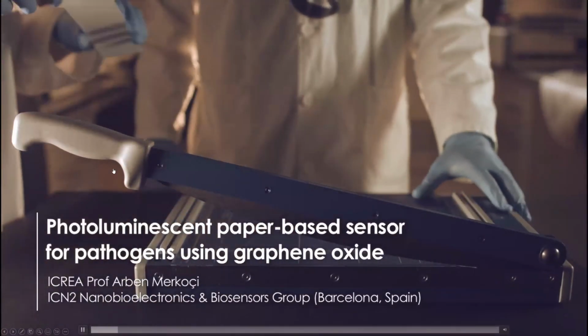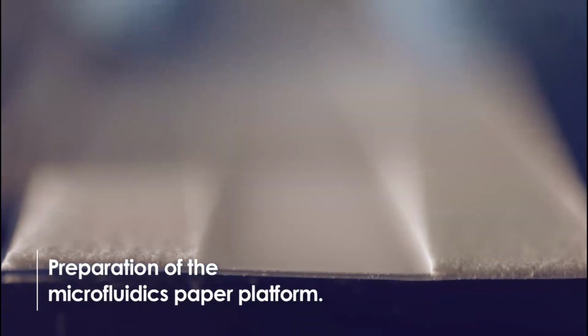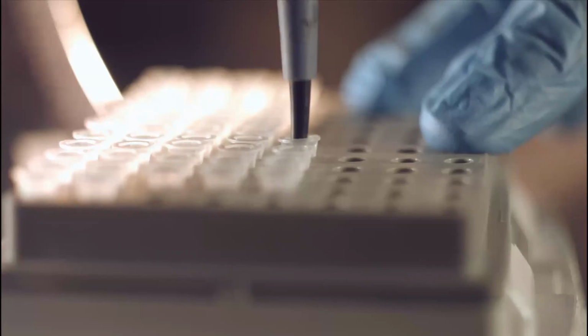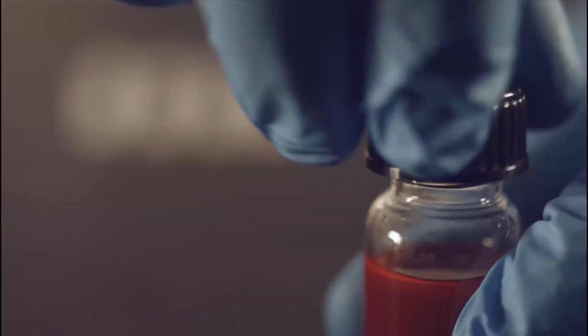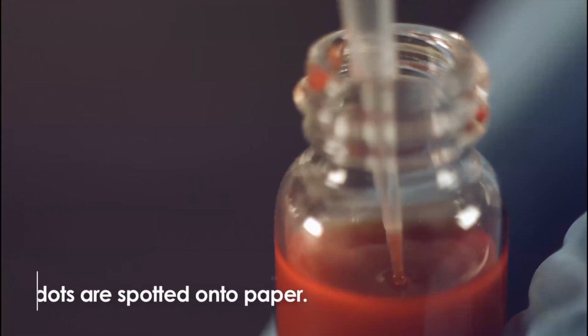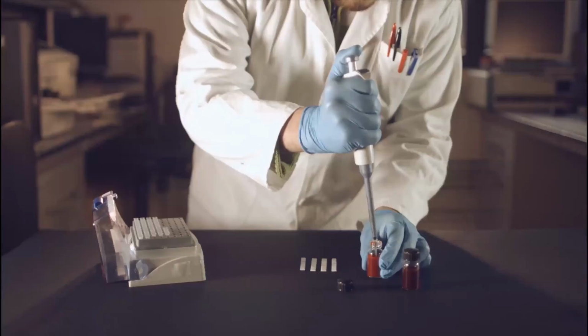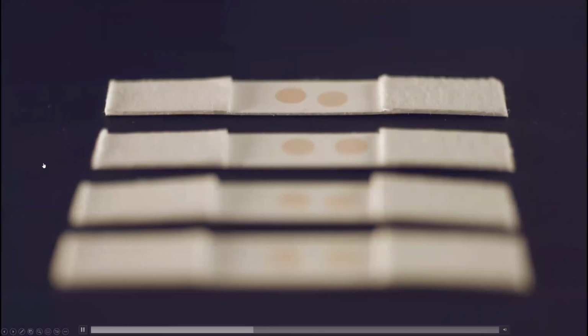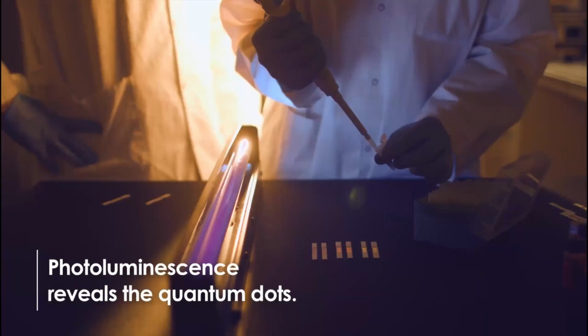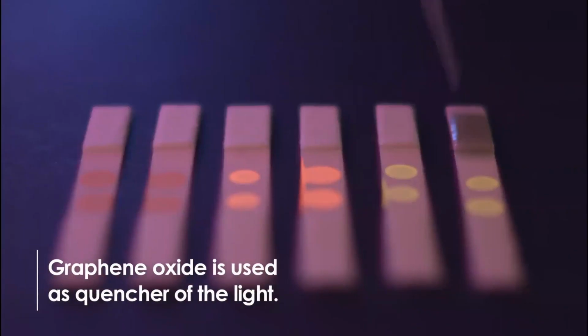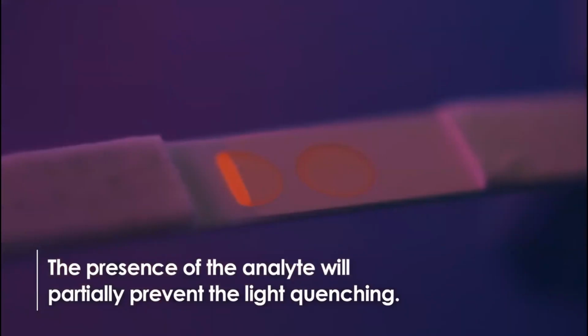So this video is showing how we prepare these devices and how we prepare for the measurements. First of all, you select the paper, you introduce quantum dots, in this case cadmium selenide quantum dots, that are spotted onto the paper, and afterwards, after the excitation of these cadmium selenide quantum dots with invisible light, you see the nice photoluminescence coming from these quantum dots. Then, adding the graphene oxide suspension, the quenching of the fluorescence occurs, and you see how this photoluminescence is quenched. So the light is turned off, and what we do is correlate this change of the light with the concentration of the bacteria.